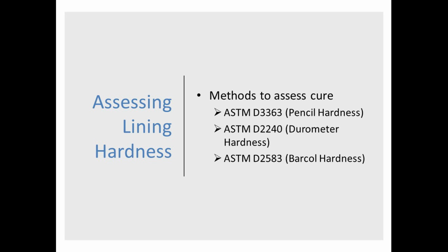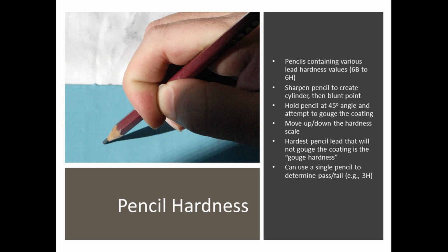The last thing I want to mention real quickly is hardness, making sure that if we have a cured lining system, that we've achieved the hardness that we need to before we put that lining in service. For thin films, we might use pencil hardness, which is D3363, not a very precise method. Calibrated pencils, traceable pencils, are getting extremely hard to get. No one uses drafting pencils anymore.